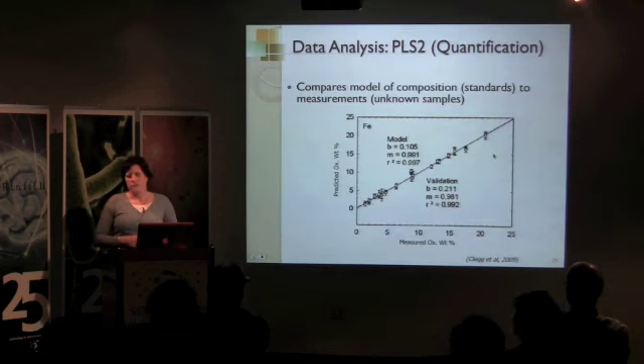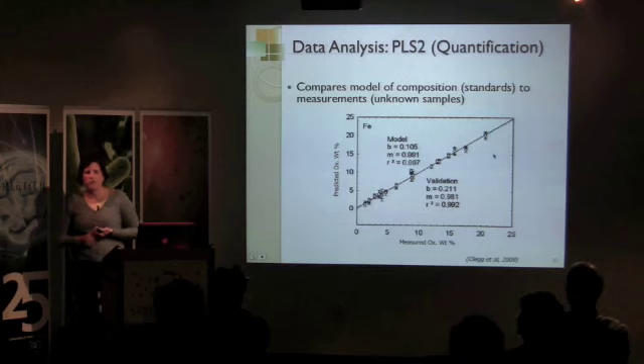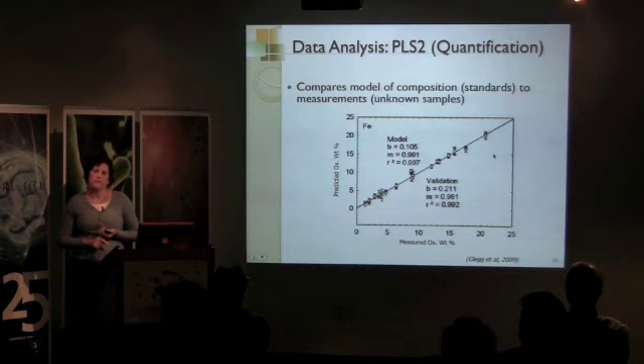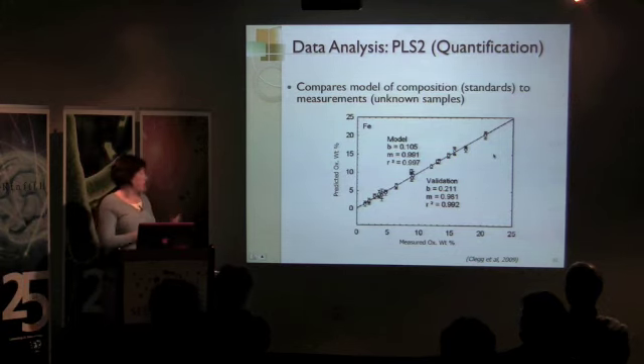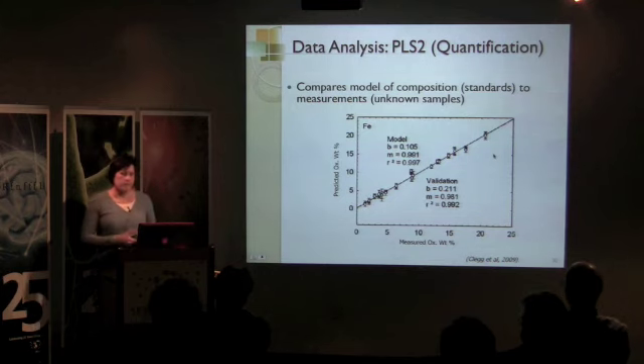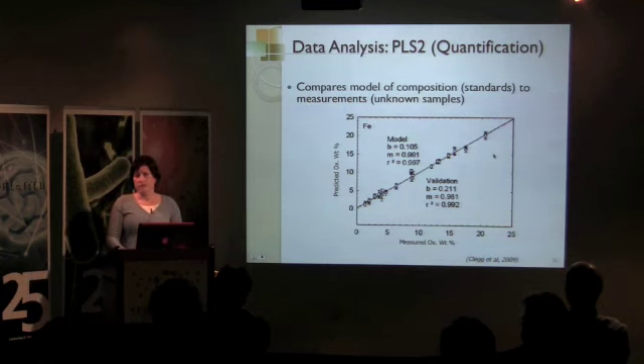One way to get around this, we found, is through doing data analysis. The last graph I showed you is just strictly from taking peak areas from the raw data. Now if we take the same data and do a partial least squares analysis, we get a much tighter correlation with a direct relation between the measured oxide and the predicted values. So this seems to be a very effective way of tightening our scatter.